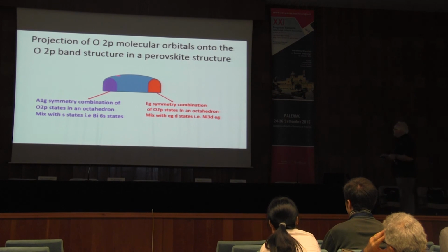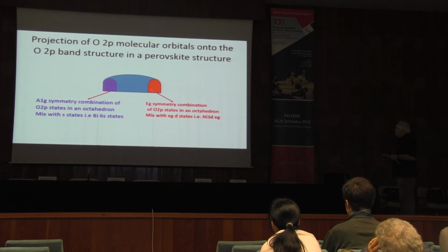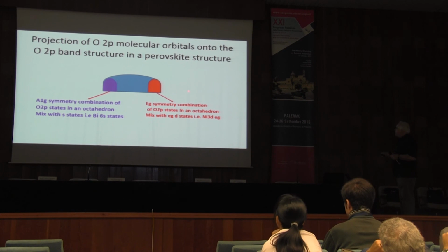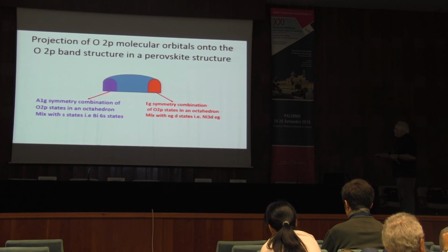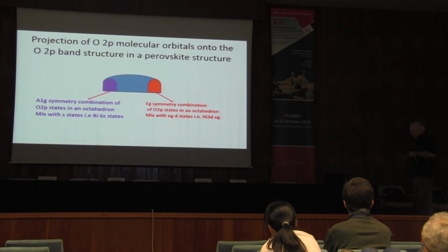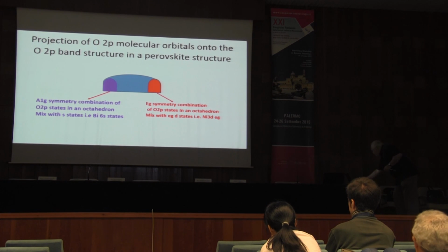If I look at the oxygen band structure, and I've just drawn a schematic, then the states that have e_g, x squared minus y squared and z squared symmetry about a central nickel or bismuth atom, they would be up over here. The Fermi energy would be here. So they would cost me little energy to move them out and empty them. That's what happens in the nickelates. Here, though, are the s orbitals, the A1g symmetry states, which are the combination of oxygen states which would mix with that 6s orbital of bismuth. Okay, so let's see what happens.